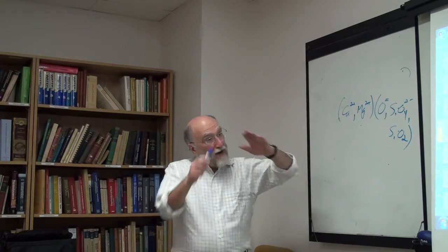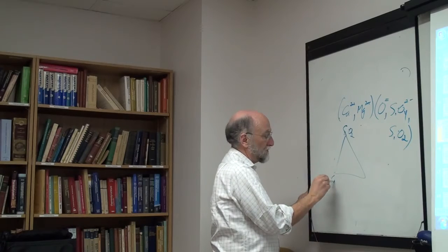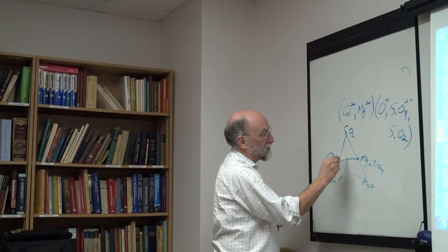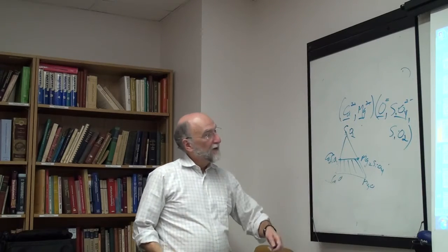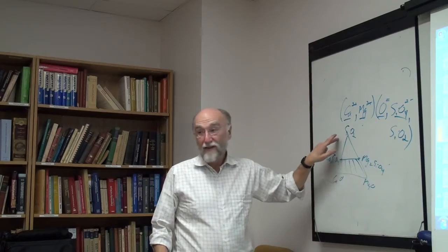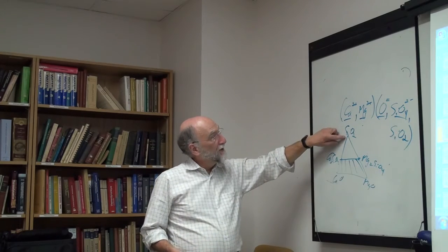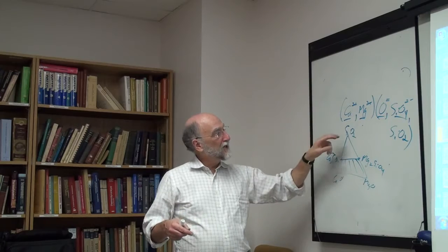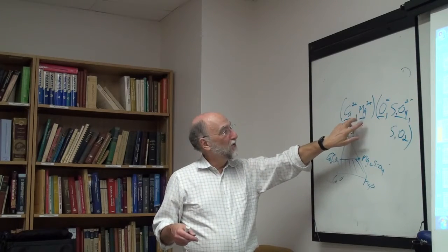In the basic region, down here in the SiO2, CaO, MgO system, down below Ca2SiO4, you really do pretty much have these four ions. This could then indicate the deviations from completeness, and up at this end you end up with nothing on this sublattice and pure silica on this sublattice. It's obviously kind of an artificial model. The ratio of the lattice sites changes until, when you get to silica, you have no sublattice 1 sites, and everything on the sublattice 2 sites is occupied by silica. You can kind of fit things, but as I said the other day, it's not terribly predictive, but at least it's a way of going about things.